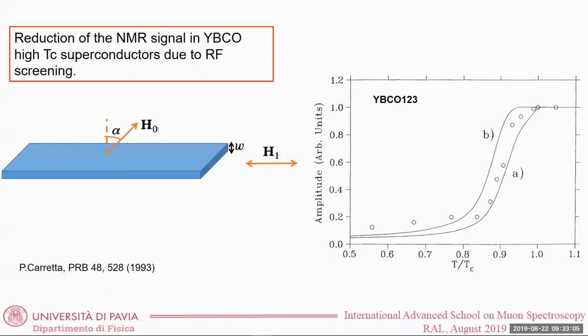Just to show you that indeed with NMR we are not probing the full sample. What I report here is the amplitude of the NMR signal in this family of superconductors as you go below TC. And as you go below TC, what you see is that the intensity of your NMR signal decreases down to about 10–15%, which is basically telling you that you're probing just 10% of your sample because of this problem. This is not a problem for μSR. And this is why μSR has been the most used technique to study the flux line lattice in superconductors. Okay.